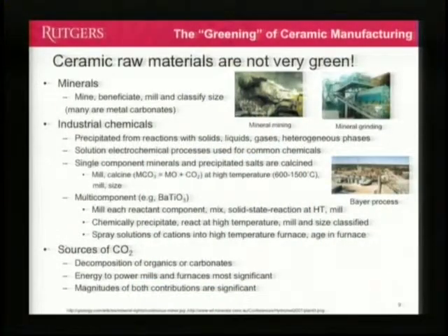If we're making different kinds of single component materials, a lot of times we'll want to calcine them before they're ready to be used as ceramics. So most frequently, they're in carbonate form and they release CO2. And that's a big deal. You're going to see that almost the same amount of CO2 that's released in the calcination stage equals approximately what it takes to fire the material. So you literally, when you work with a carbonate, double your CO2 that actually comes out.